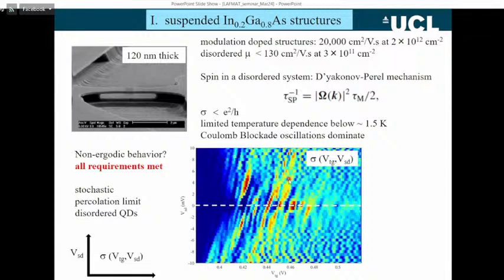As I say, what happened in this particular device is if we apply a DC voltage now, so this data on the false color image I'm showing you here, the y-axis is DC voltage, so that's DC voltage applied across the ends of the wire. The x-axis here is the top gate voltage. As we put charge into the system, it starts to conduct, but we only get this Coulomb blockade. The color here is the current flowing through the system. So we can only get a current flowing through the system when we have the condition for a Coulomb blockade. So that's determined by this gate voltage.